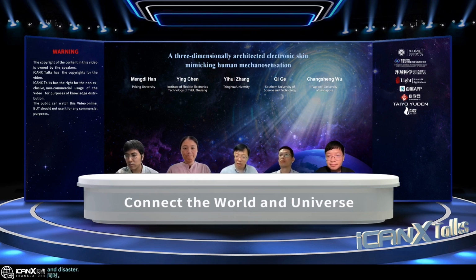And the surface curvature is quite sensitive, and it can give you different pressure distributions. So in many cases, the pressure distribution and the strain distribution are equivalently important in the measurements of the elastic modulus and shape. Because of this coupling, and because our device is fully decoupled, it can give better prediction accuracy of the measurements.